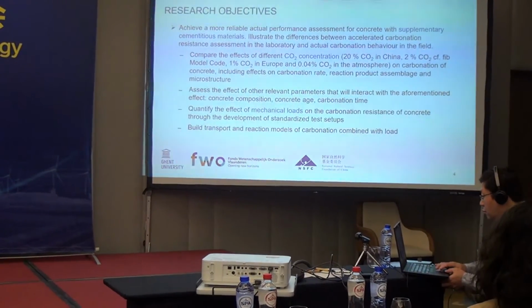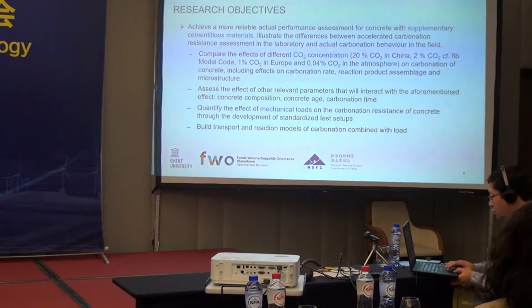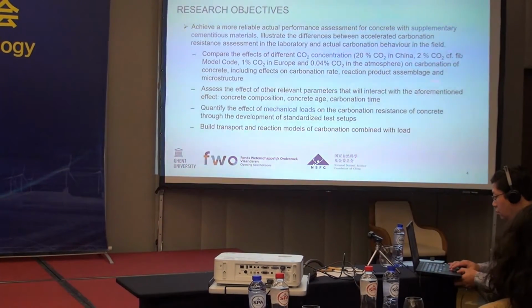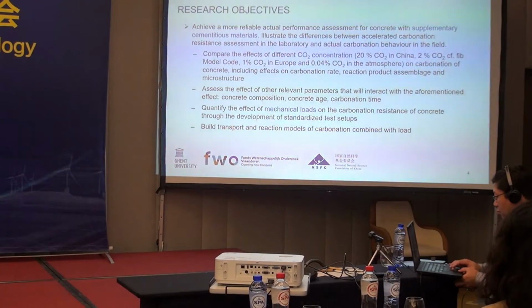And here in Europe, generally we test at 1% carbon dioxide, or 2% if we follow the FIB Model Code, whereas atmospheric concentration is around 0.04%. But in China they have a different standard and they test at 20% CO2. So we wanted to see the effect of the concentration during accelerated testing on the results. And in addition, look at other parameters like concrete composition, age, carbonation time, and so on.